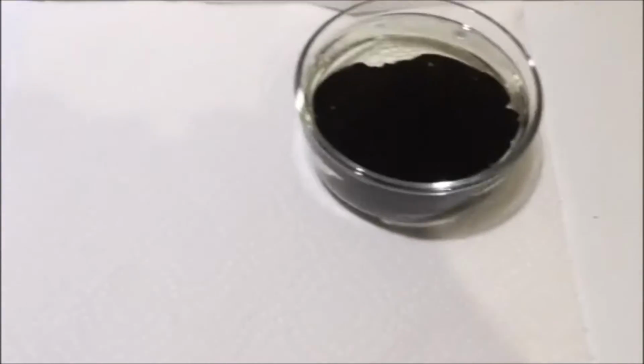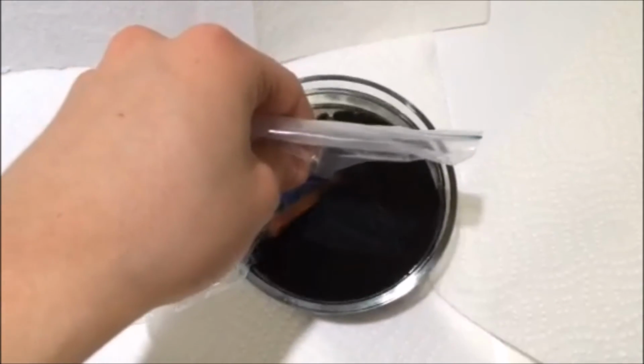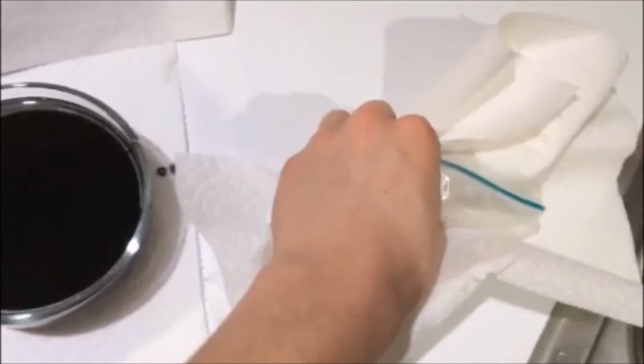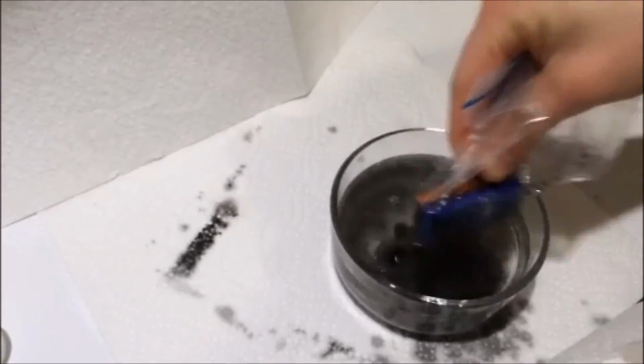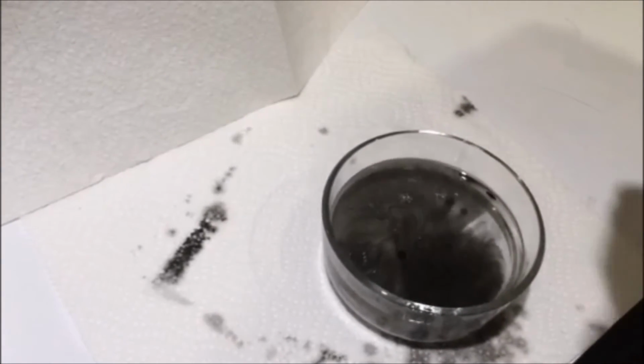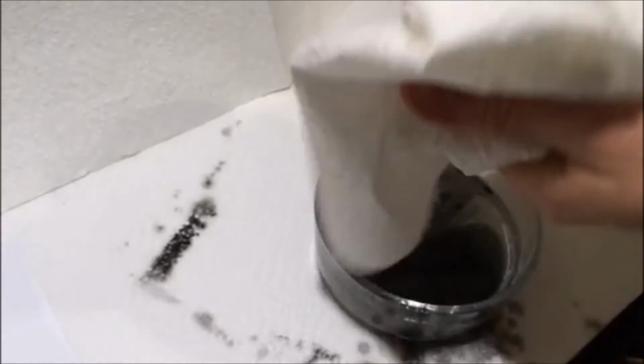As the oil coated the iron oxide, it became oleophilic and hydrophobic, which means it repelled water and remained suspended in the oil. Then, a plastic bag was placed around a neodymium earth magnet, and it was then submerged into the oil 15 times. Each time, a paper towel would dry off the remaining oil and water. After the end of 15 trials, the remaining oil and water levels were measured in the graduated cylinder.